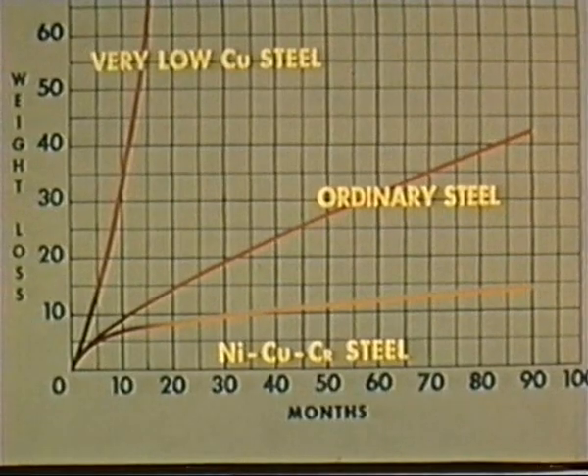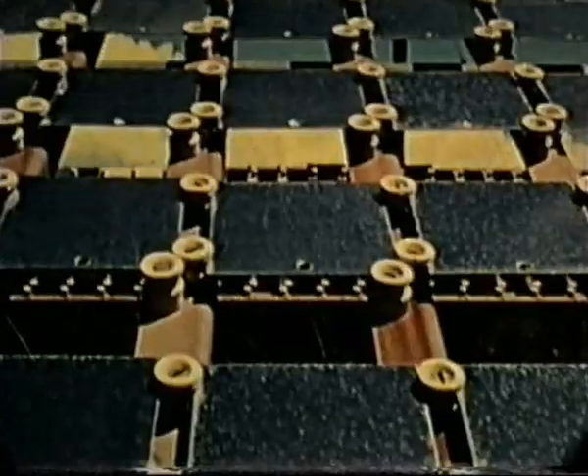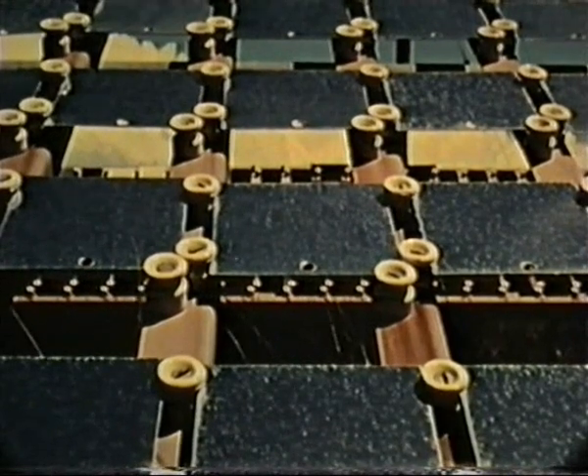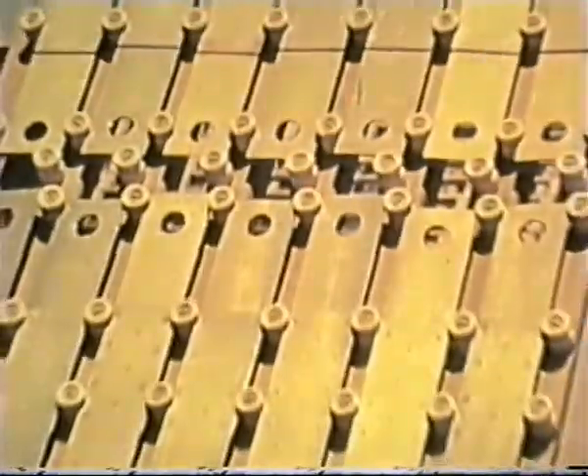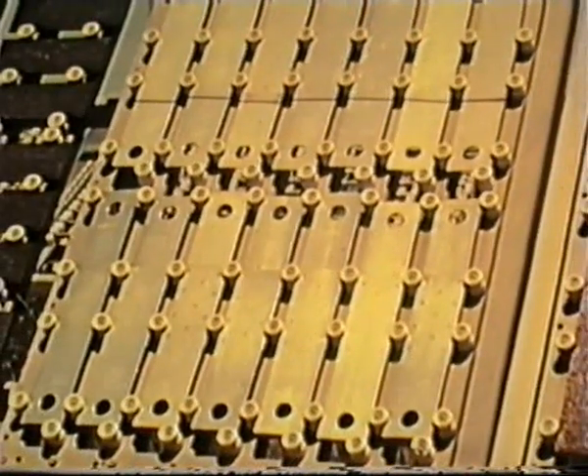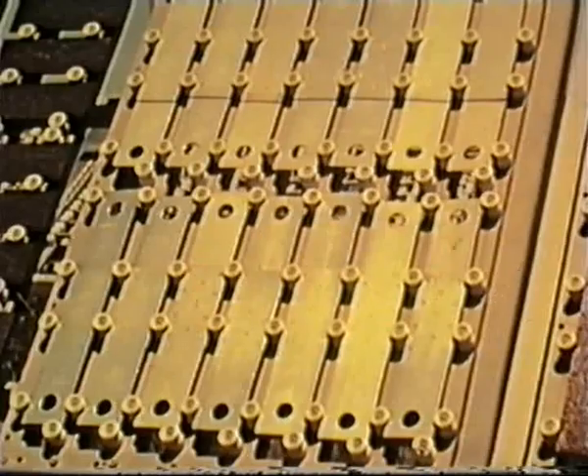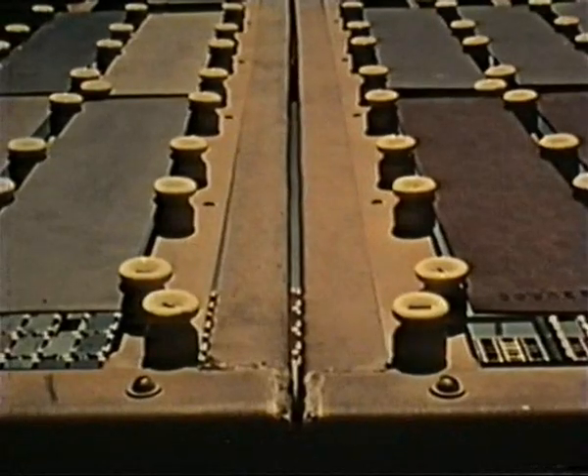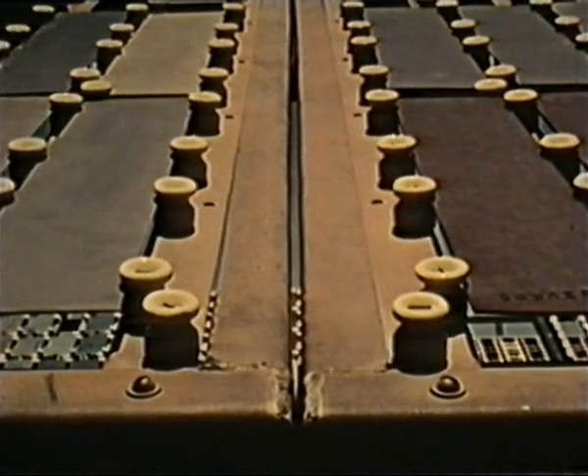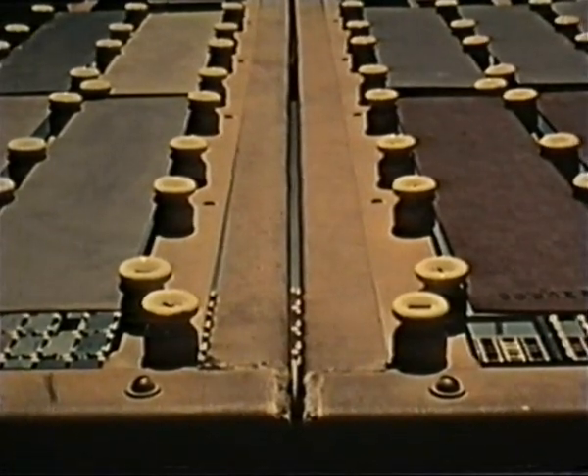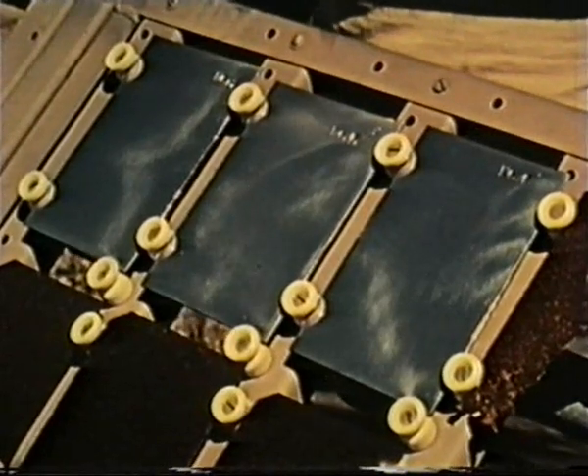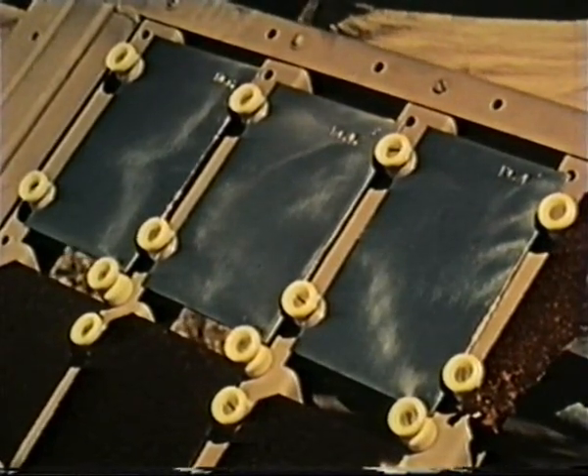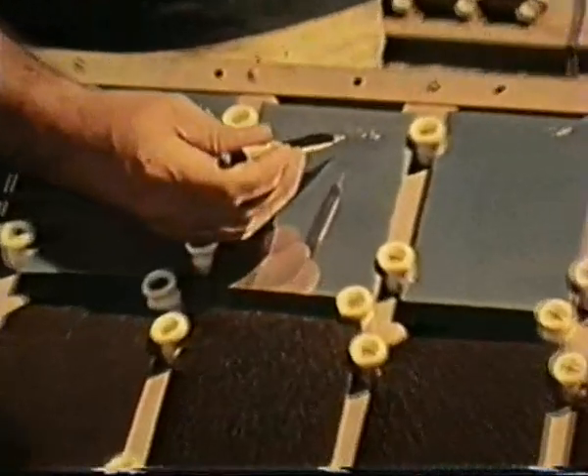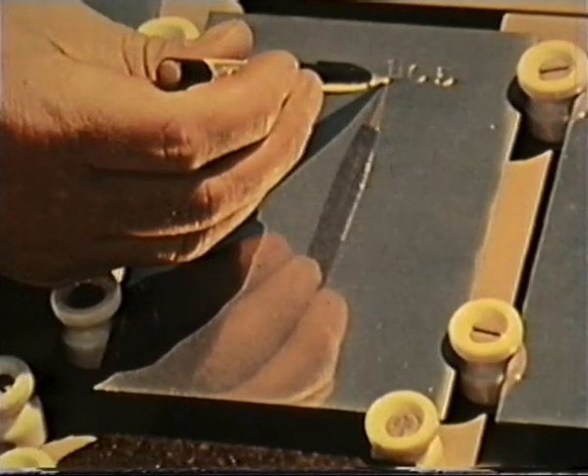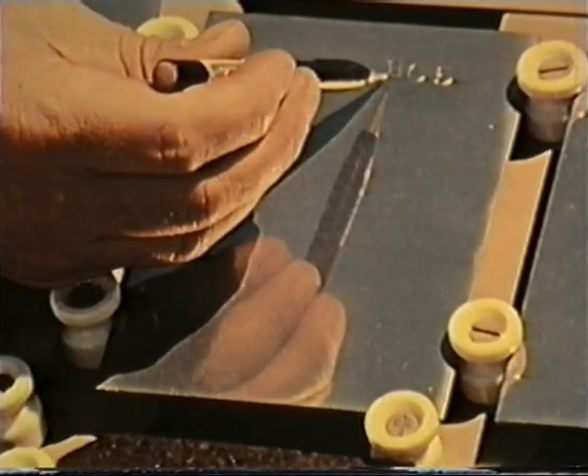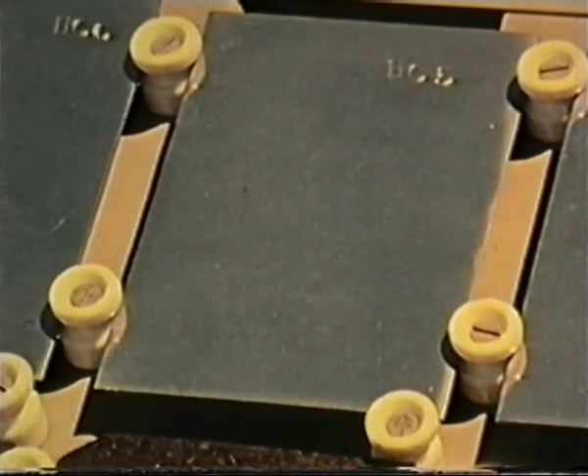Other alloys, of course, are even better than the low alloy steels in resisting atmospheric corrosion, and after many years continue to reflect the blue of the sky. For example, here are some panels of 18-8 chromium nickel stainless steel that have been exposed for over 10 years. Notice also how the Monel nickel-copper alloy racks, also in use for more than 10 years, have developed only a uniform superficial tarnish. And here is complete resistance to corrosion, provided by the complex nickel-chromium molybdenum alloy known as Hastelloy C. This specimen continues to serve as a mirror after more than 30 years' exposure at the atmospheric testing site of Inco's North Carolina laboratory. It has never been cleaned or repolished.